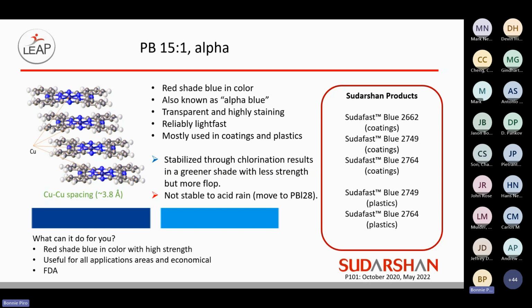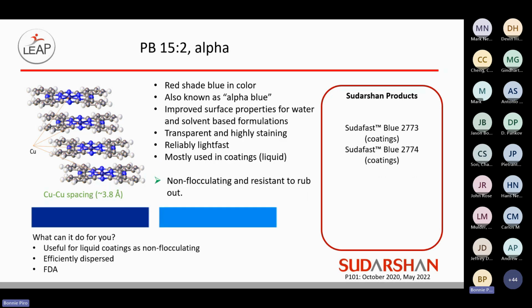It should be noted that if you are using it for an exterior coating or plastic that does not have a clear coat over top of it, it is susceptible to acid rain, where the color will shift considerably. So our suggestion is to move that particular formulation to a Pigment Blue 28, which is not susceptible to acid rain. So it's a very useful pigment for all application areas, and it does provide some economical formulation space. And of course, with the FDA, it is also helpful.